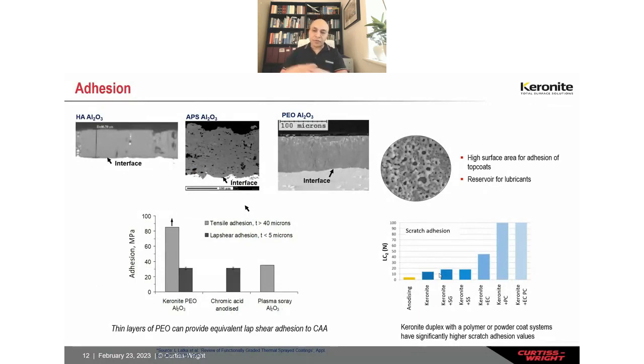Adhesion is another interesting feature. I would like to show you 3 pictures here. On the very left is the hard anodized coating, very good interface, good adhesion. This is a thermal spray, the plasma sprayed alumina, with mechanical keying primarily. You can see those from grit blasting, porous coating. This is the PEO alumina here, very dense, very well adhered to the interface. And this plot here is the ASTM D4541 pull adhesion test. The adhesion of the PEO coatings was in excess of 80 megapascal, quite a lot higher than plasma spray alumina.